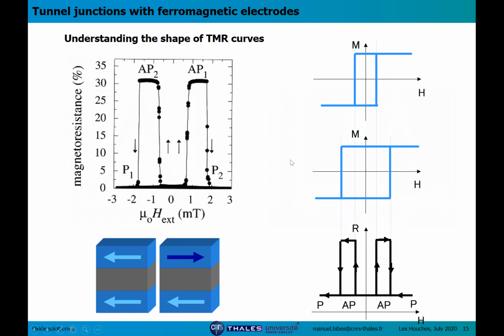I think this is pretty straightforward. Maybe you know about this already. This is another curve which has a slightly higher magnetoresistance and very flat values of the resistance on top of these two plateaus. To get TMR, you need to combine two ferromagnets that have hysteresis loops with different magnetic coercive fields, so that when you sweep the magnetic field, there is a range in field where you have an anti-parallel alignment of the magnetization of the two ferromagnets. In this case, with these two hysteresis cycles, in this range of field, one will have switched and the other one will not have switched yet. So you reach this anti-parallel alignment, and then the resistance is going to be higher. And you get the same symmetric behavior as you sweep the field back towards positive values.